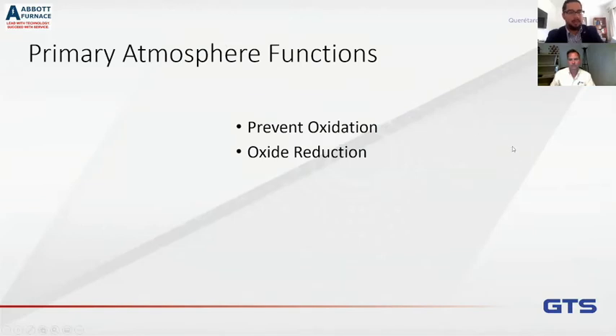Perfect. So, well, we need to talk about why we use atmosphere. Yes, and that's why it's the workhorse, but it does two primary things. It prevents oxidation, and it reduces the oxides that are on the surface. Correct. Because in brazing, the first step is you heat up the product and then you reduce the oxides so that the filler metal can flow over the surface and form the alloy and form the bond. If you allow that oxide layer in there, it acts as a barrier between the filler metal and the base metal, and you won't get bonding. So those are the two principal functions of the atmosphere: keep air out of the furnace, and reduce the oxides on the surface of the metals.